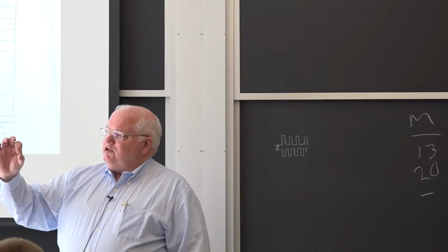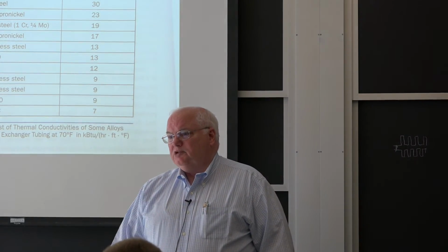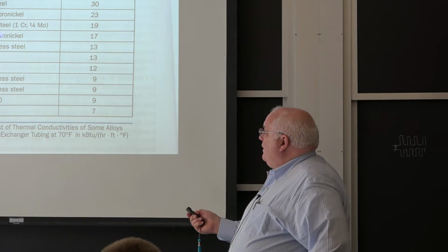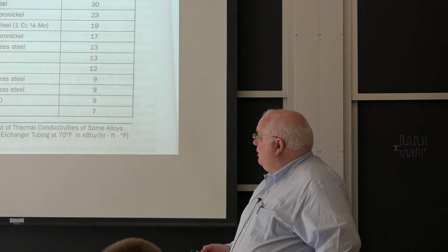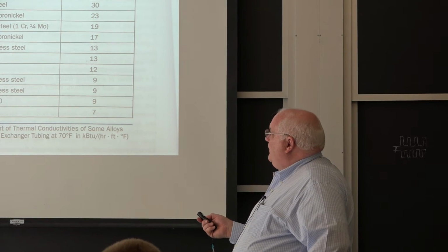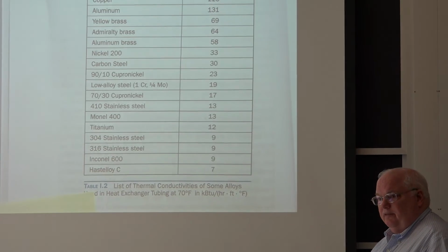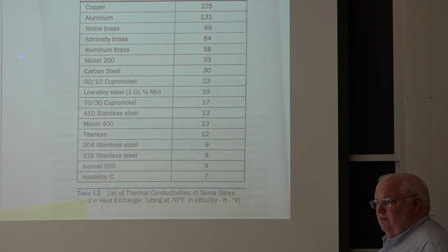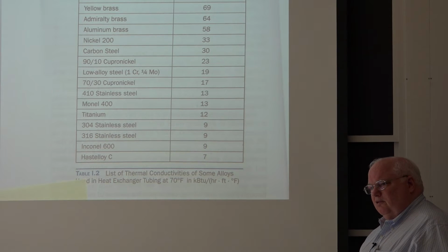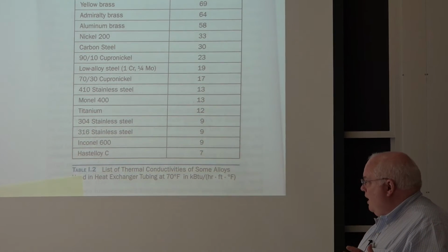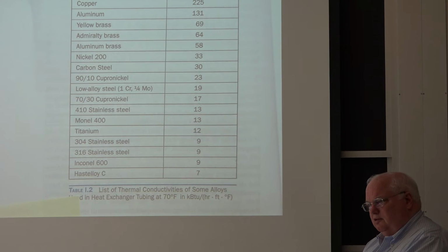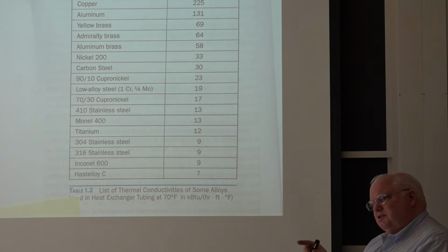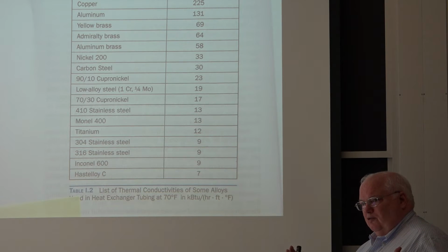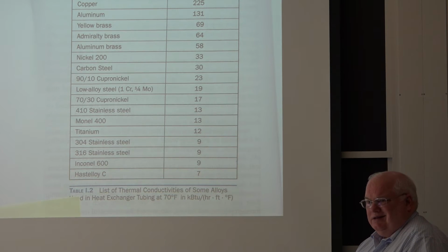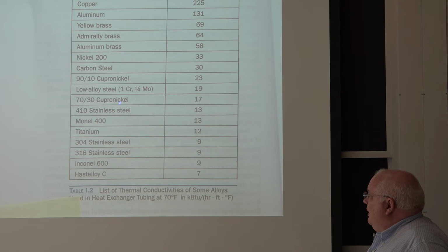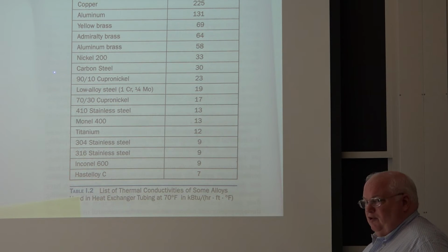There's a lot you can change: the diameter of the tubes, the water flow rate through the tubes. Although, if you change the water flow rate, I had a heat exchanger up here at the Mormon Temple in Belmont, and they originally had put in copper as the heat exchanger material, okay? And after 1 year, they knew they had a little leak in there somewhere, and so they took the top off, and up at the tube sheet, the plate that holds all the tubes, where everything had turned because of the higher speed, they had corrosion on the copper because of the solids in the water and stuff. It caused erosion. And I wanted to go to 7030 cupro nickel, but they couldn't get that.